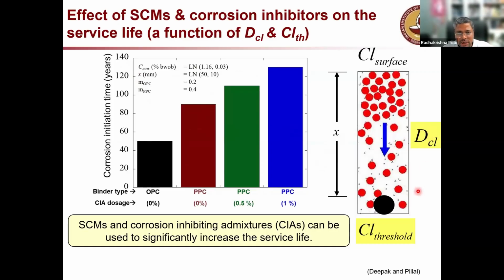One for the concrete and one for the steel concrete interface. Look at the right side. This is where I started the discussion with. Same chart. You have these red circles, which are the chloride ions penetrating or diffusing towards the steel reinforcement. And this is the steel reinforcement. So the speed by which these chloride ions penetrate, if you can reduce that by using SCMs, you get more service life. That is one aspect. The other aspect is chloride threshold. The amount of chloride required at the surface of the embedded steel, if you can increase that, then also you enhance the service life. So here by using the SCMs, we are reducing the speed of penetration of chlorides, and by using the inhibitors, we are increasing the chloride threshold value. So this is a synergistic effect. Both parameters work: the chloride speed is reduced and at the same time the demand is increased. So then you get really long service life.